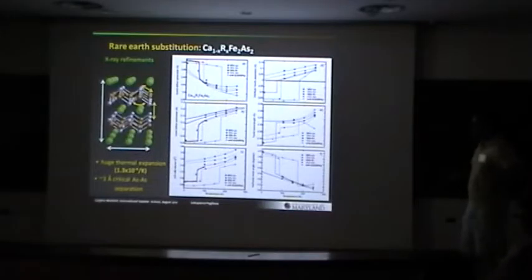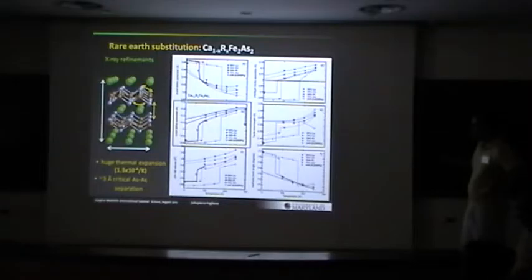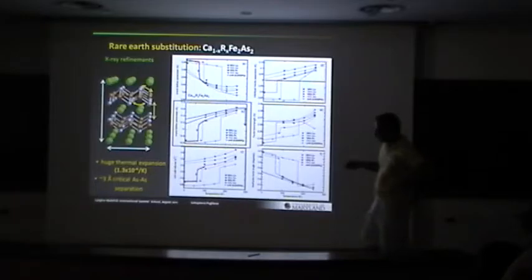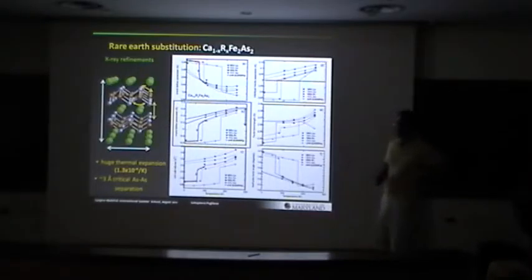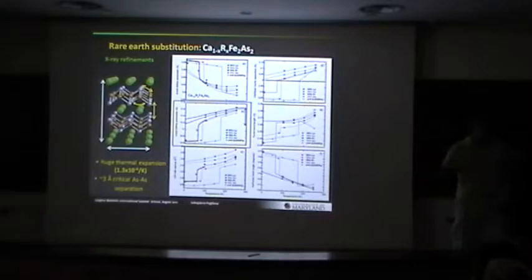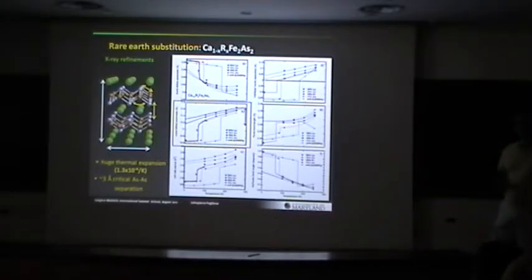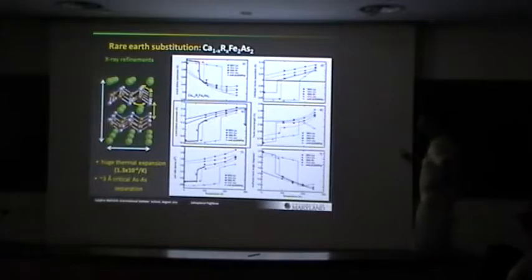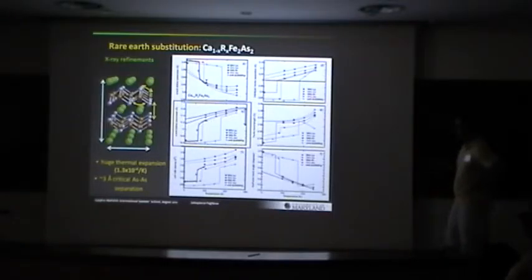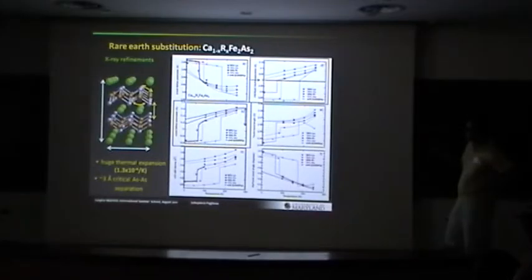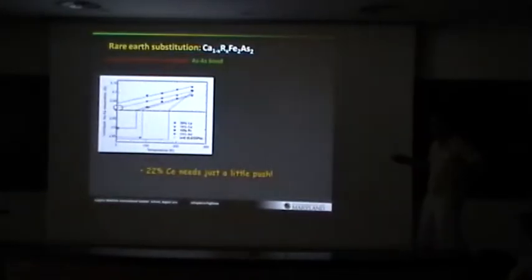Okay. Here's a mess of data, but I just want to focus on two things. First of all, the thermal expansion that we see here, even in the samples that do not undergo the collapse, is huge. It's actually 130 × 10⁻⁶. So this is one of the largest expansions I can find in any reference books. So that's quite neat. The other thing is we've done some X-ray scattering, single crystal X-ray scattering as a function of temperature. And this is the interlayer arsenic-arsenic separation here. I'll blow that up in the next slide.